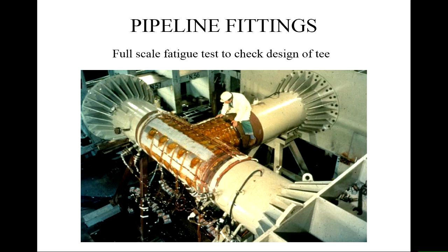This is incredibly expensive. So to qualify your fitting for offshore use in particular, you have to do this sort of testing. It's very expensive, and therefore there aren't very many suppliers of fully qualified materials, and they tend to be older materials designs because of the qualification tests. Because line pipe's easy to test and prove, fittings are much more difficult to prove.